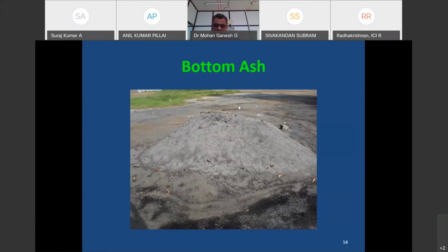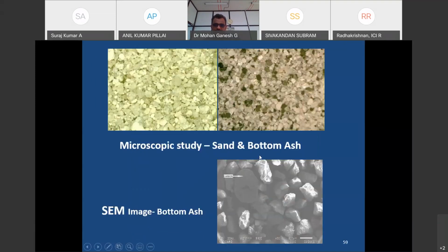Okay, so the bottom ash looks like sand, but it has some impurities like carbon and ferric oxide. So we have done the microscopic study. This is a sand, this is a bottom ash. Both look the same. Here only the carbon particles or ferric iron particles are there. This is the same image of the bottom ash. This is the unburned carbon. You can see the unburned carbon here. The scale is 500 micrometer. It was done in the year 2011.